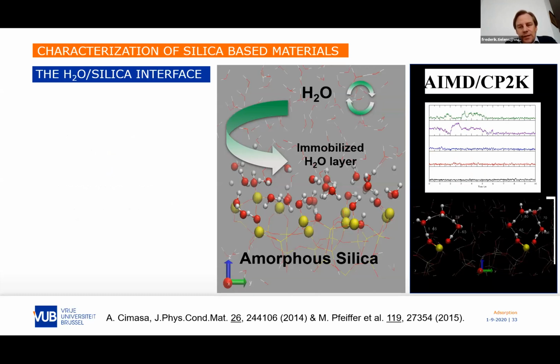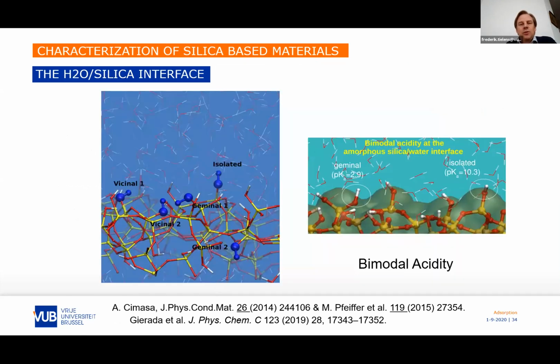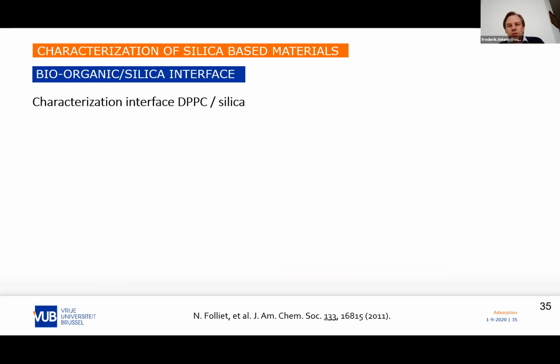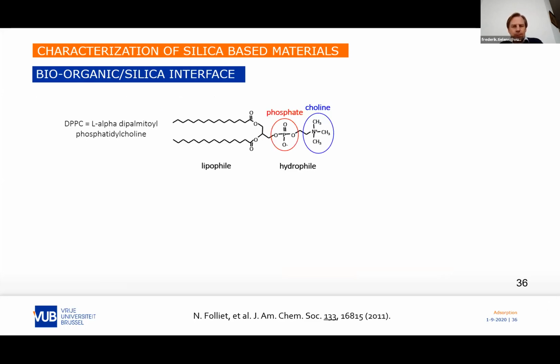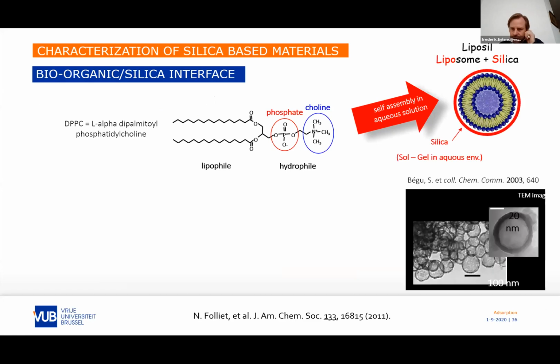And there are quite important properties linked to that, especially what is known as the bimodal acidity property of silica. So you have different types of silanols that I show here, and we can go to extreme sites. We calculated pKa's of these silanols, and we found extreme values of 2.9 to 10.3, which shows that you have acid and basic sites. So very extreme sites. In fact, you have to take into account that you have different types and a distribution of types of silanols at the surface. Now, how the interaction with water occurs, I will go further. Here I will go fast, maybe, and I will stop after that.